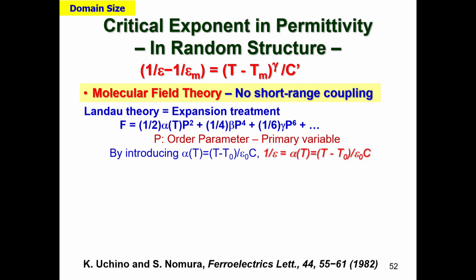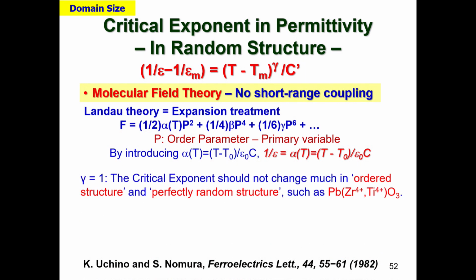Basically, the inverse permittivity is proportional to the temperature to the power of gamma. In molecular field theory, you are usually familiar with this situation. Therefore, the Curie-Weiss law, where gamma is equal to 1, is presented. Gamma equal to 1 is usually true for a completely ordered structure or a perfectly random structure such as PZT. However, Zr and Ti have some interactions and the situation is different.